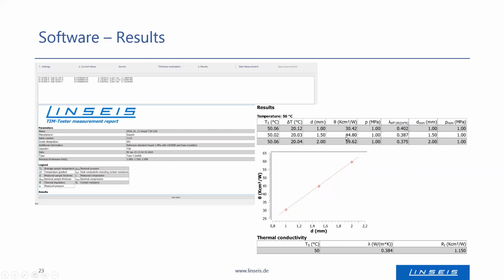In this report, one can also see the graphic representation of the thermal impedance dependence on the sample thickness. In the ideal case, it is a linear correlation, and if some of these points do not fit to this line, something might have gone wrong.